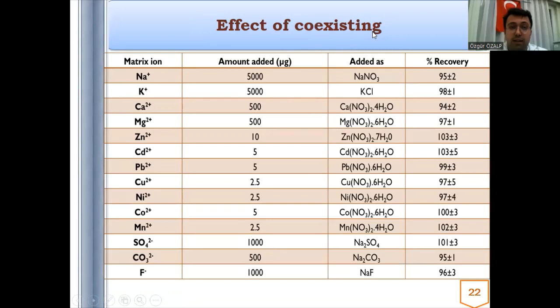And then the last optimization parameter, the effect of coexisting ions and interference. For matrix ions, you can see cations and lastly anions, including most heavy metals. The amounts added are in micrograms, as salts or compounds. Lastly, for recovery and standard deviation, recovery increased to 94 and about 100 percent. These are our best results.